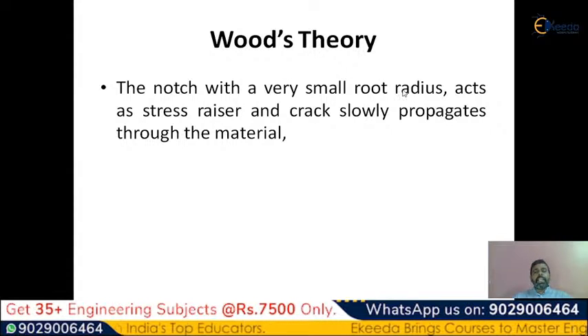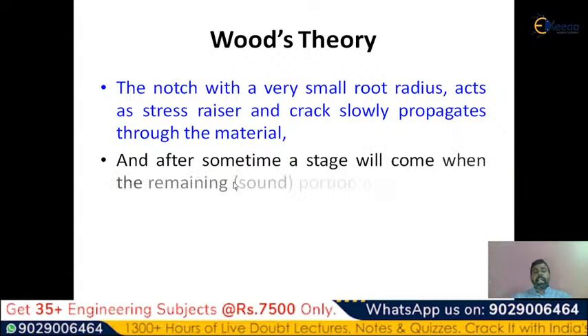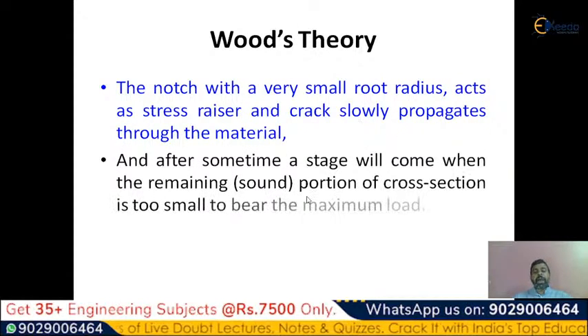The notch will be generated. A very small root radius acts as a stress riser. I already said that these notches act as stress risers, stress concentrated areas, and the crack slowly propagates through the material. So that is going to be the biggest problem for the material. Now you can observe here. It also says that after some time, the stage will come when the remaining portion of the cross section is too small to bear the maximum load. Any material cannot bear the maximum load.